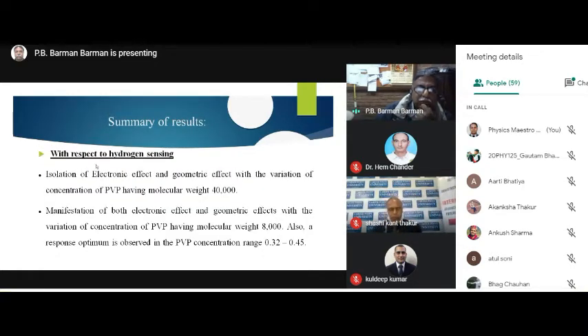With respect to hydrogen sensing, the isolation of electronic effect and geometric effect occurs with variation of PVP concentration having molecular weight of 40,000. We are still working on it to optimize this result, but definitely 32% is the best in our case. The manifestation of both electronic and geometrical effect is seen with variation of PVP concentration having molecular weight of 8,000.